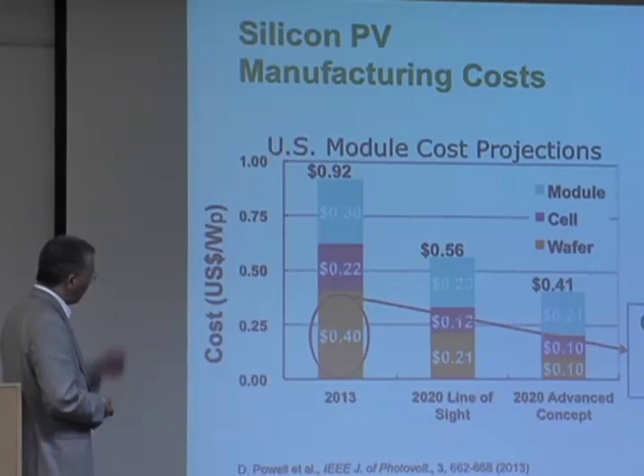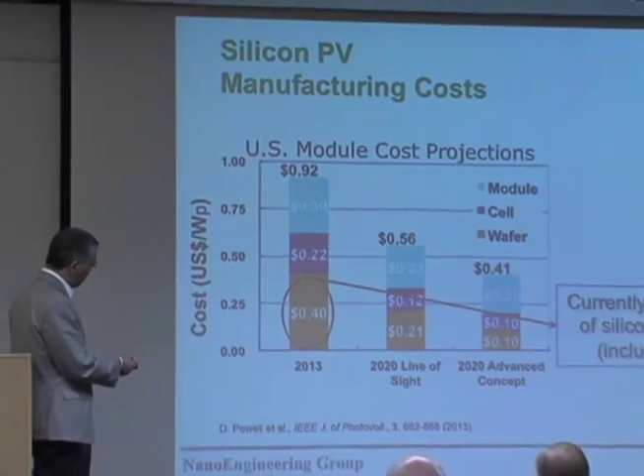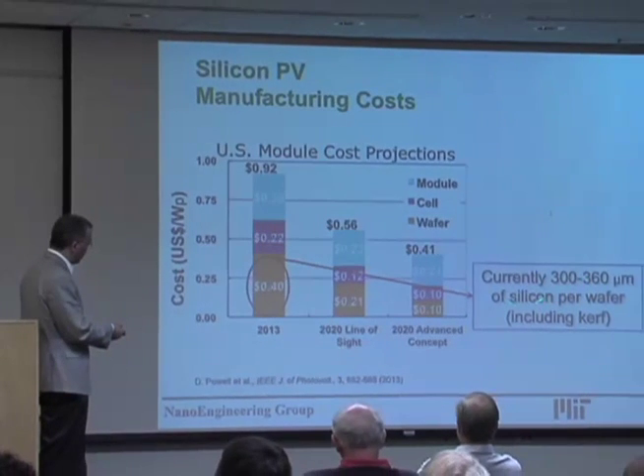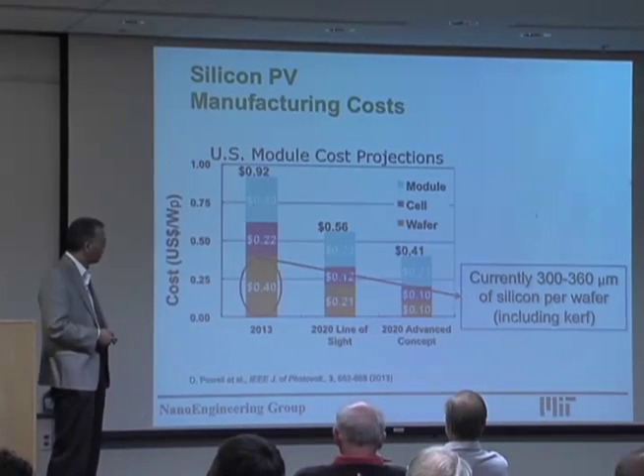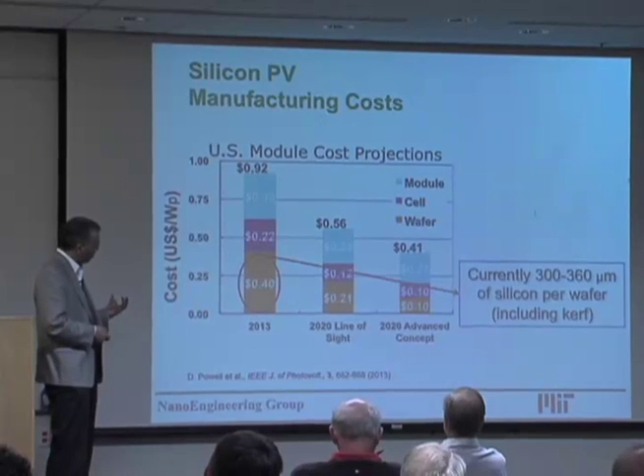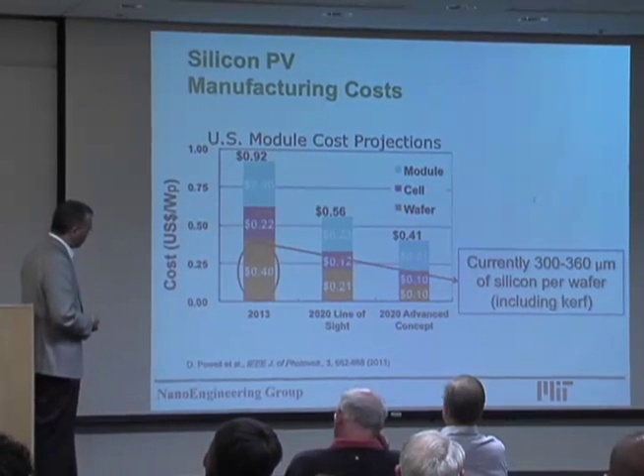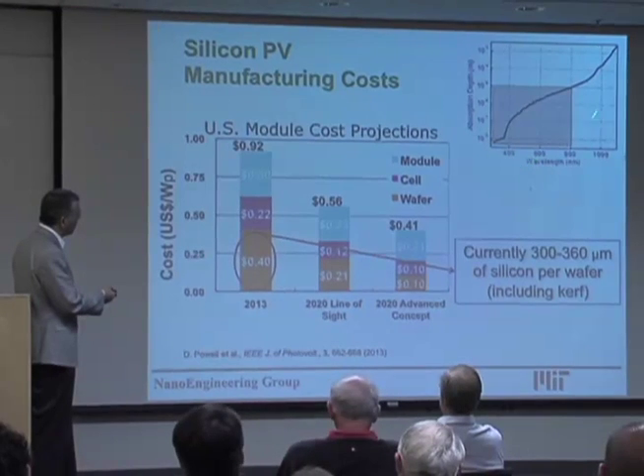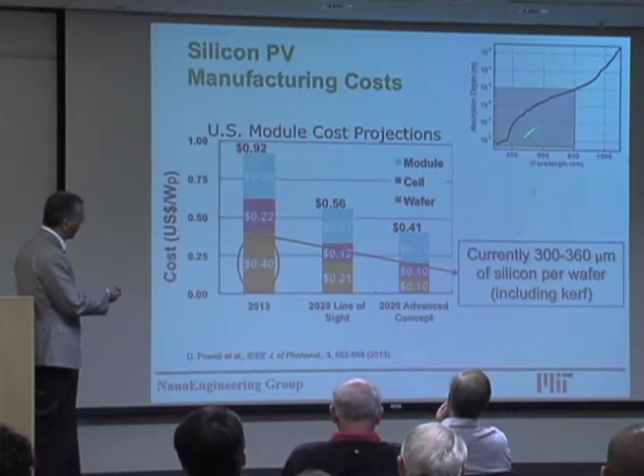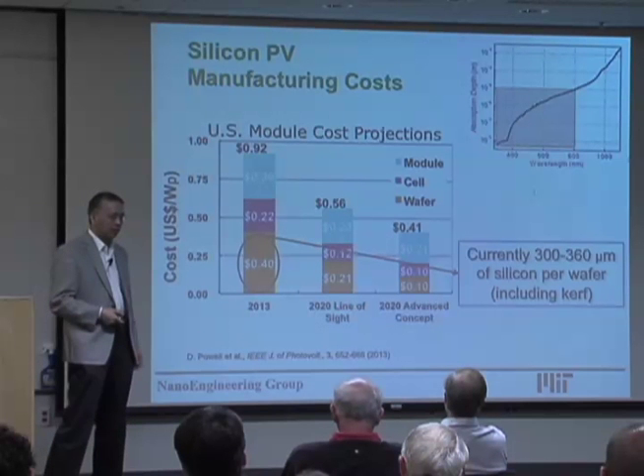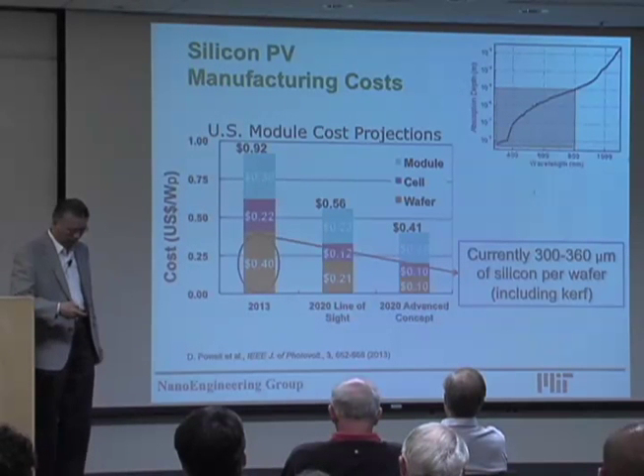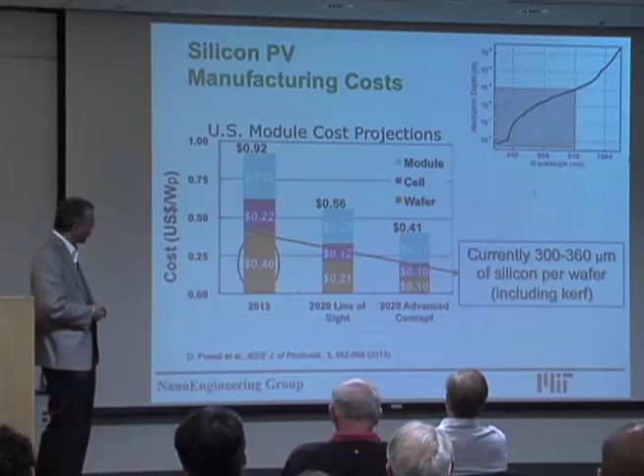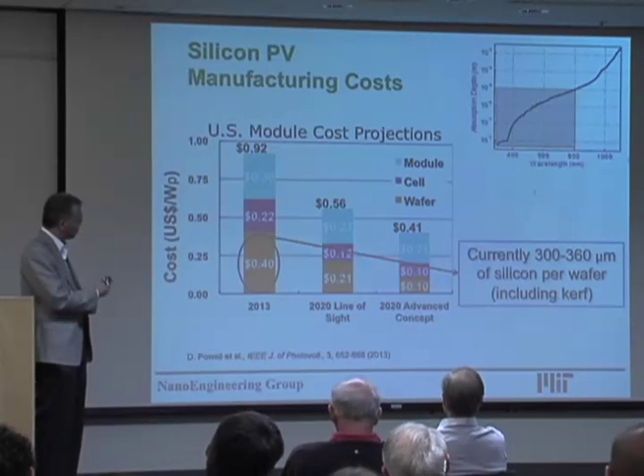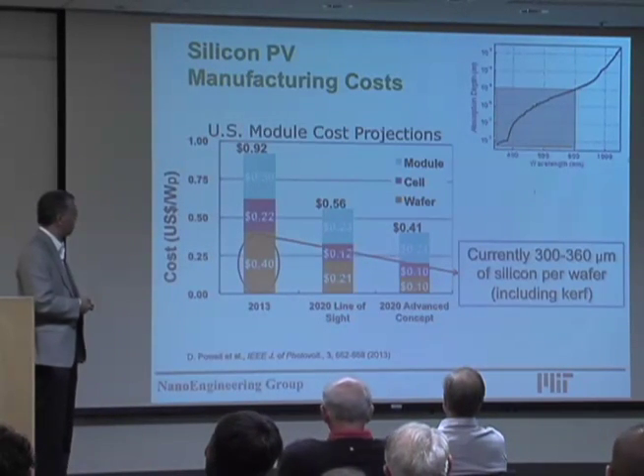Most of the current silicon modules are based on wafers with a thickness of about 300 microns. One of the main reasons for this thick wafer is absorption. Of course, silicon is an indirect gap, so absorption is not good, and you need a much thicker wafer. So a lot of people are doing light trapping, trying to use much thinner material to get similar absorption and reach a reasonable efficiency.